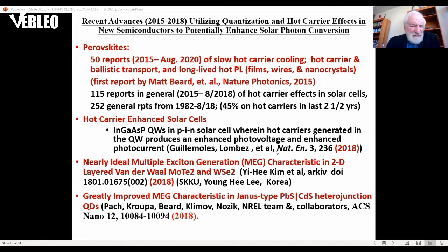But this material, and there's quite a large family of types of perovskites that are being studied now, has almost magical electronic and optical properties. So they're very good for PV. They're very good at slowing the hot electron cooling. So hot electron or hot carrier effects are being examined in these types of solar cells, as well as in conventional solar cells that currently have an efficiency equal to or even exceeding silicon.